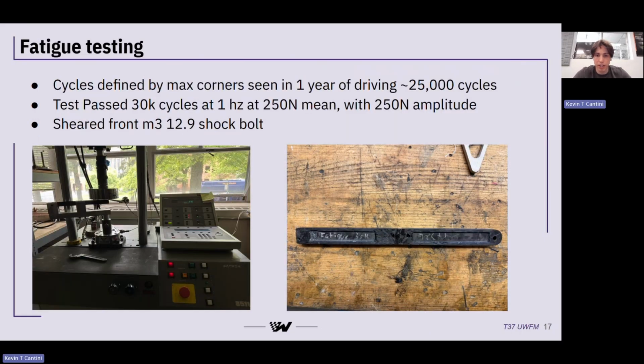For fatigue, we defined our cycle count from the worst corners in a year of driving, about 25,000 cycles. A Gen 1 arm passed 30,000 cycles at 1 hertz with a 250 Newton mean and a 250 Newton amplitude. The M3 shock bolt was what actually ended up failing.